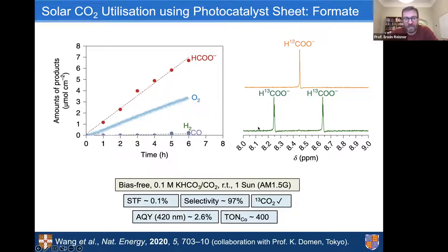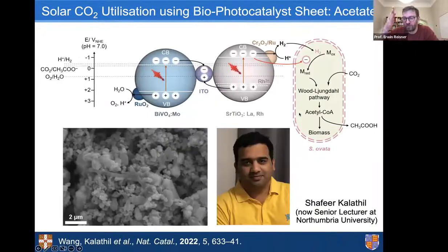And if you do isotopic labeling, I really strongly recommend to run the proton NMR to look at this very characteristic splitting and not only the carbon NMR, because this just does not show you any of the splitting pattern at all. We could expand this here with Shafeer Kalathil, who also is now a senior lecturer at Northumbria University, and has moved on to his independent position.